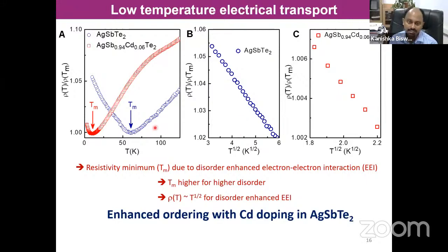The coherence is destroyed if we have more electron-phonon coupling in this material. On this side we see an increase, and the minimum temperature indicates how much disorder we have in this material. If the minimum temperature shifts towards lower temperature, that means we have less disorder, so we have delocalization of electron states. We need delocalization, not localization. This AgSbTe2, which is intrinsically disordered, shows a minimum at 60 Kelvin, 62 Kelvin.